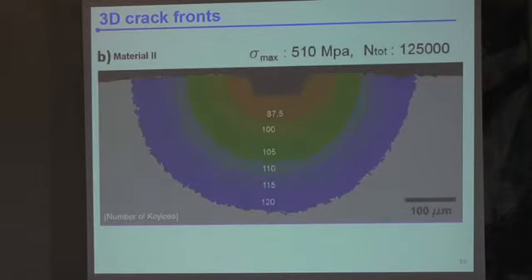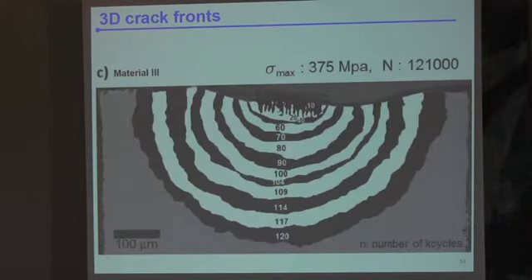Material number 2 is fairly the same, unfortunately. It's really a nearly perfect half-penny shape, with an angle here which is close to 90 degrees. And again, different microstructure. Actually, in that case, it's a different strain level, but a very regular crack front. So to make it look a bit different, Pablo put them in black and white, but unfortunately the message is the same. For material number 3, it's pretty much the same, right? So very regular crack front, and not much interaction with the microstructure.